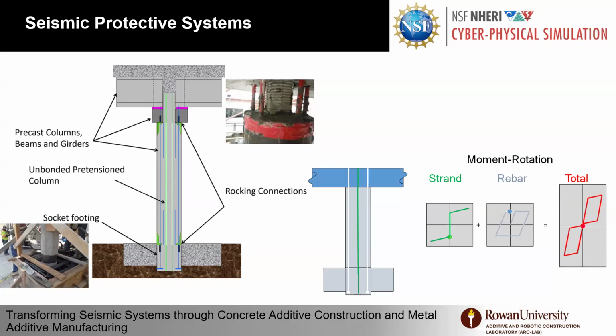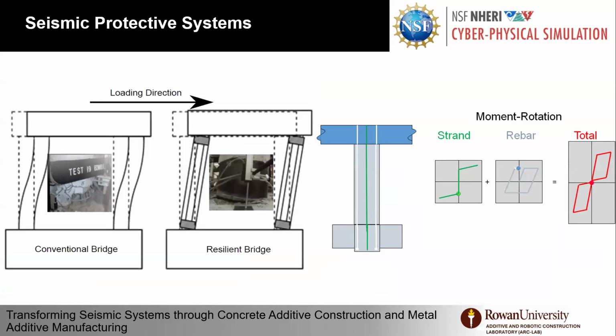So the system relied on the pre-tension to self-center, while the rebars dissipate energy, but it was an internal mechanism using yield. As you can see in the moment rotation curve, you can achieve self-centering. We compared the system to a specimen tested in 2004 as a conventional bridge system with normal design, and we observed a lot of concrete damage, rebar exposure, buckling and rupture, because we actually shifted the behavior from flexure buckling into a rocking behavior.